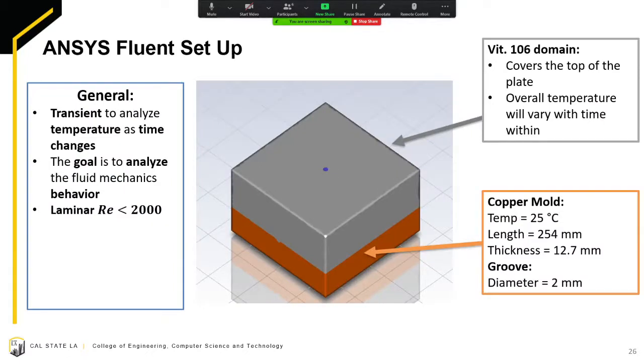The goal of the fluid simulation is to analyze the fluid dynamics behavior of the molten BMG. To determine whether the material will have a laminar or turbulent flow, we calculated its Reynolds number. Using the parameters of the disk design, the team calculated the theoretical speed of the molten BMG. The speed was derived from the circumference of the disk and number of revolutions per minute. The theoretical speed of the molten BMG is 0.66 meters per second. If the molten BMG fills up the groove on the copper mold, the calculated Reynolds number was 1,058, which gives the molten BMG a laminar flow.